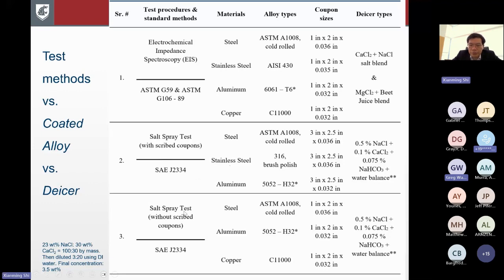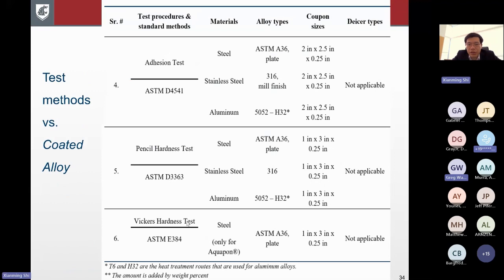In this case, for the salt spray test, the series 2 is with the scribed coupons. Basically, you have an X marked on each coated coupon, and the series 3 is without the scribe. Especially in some cases, the coating is too soft, or just a grease. There's no easy way to do that scribe. So depending on the situation, there's a little bit of deviation from this scribing procedure.